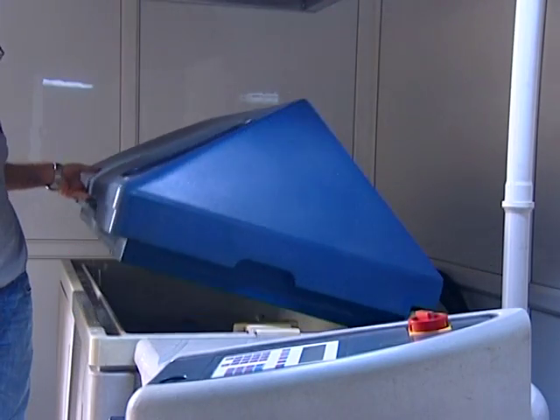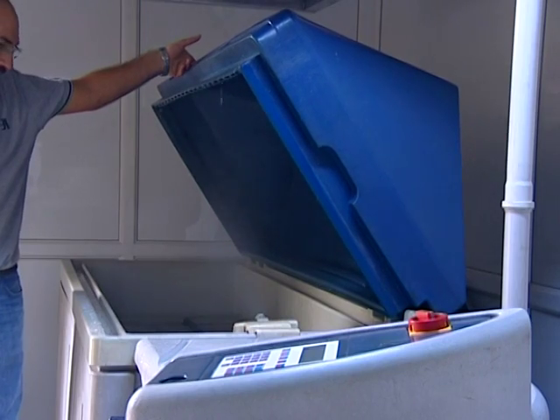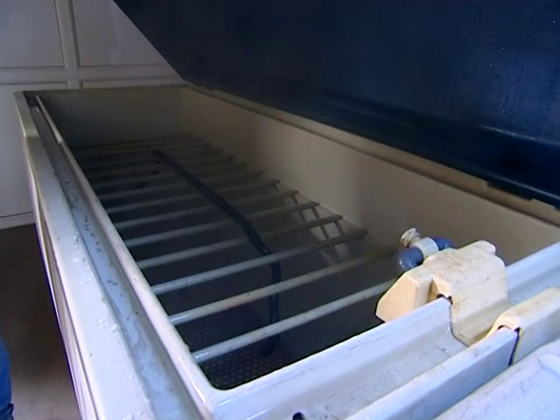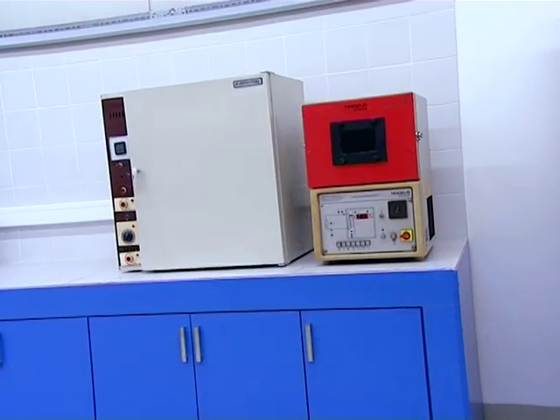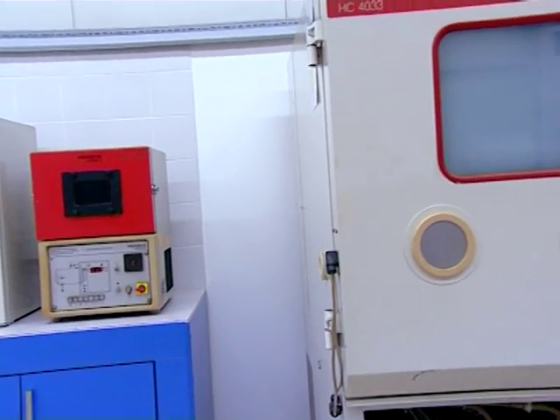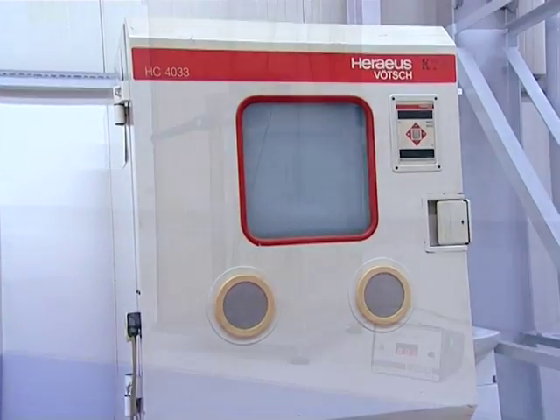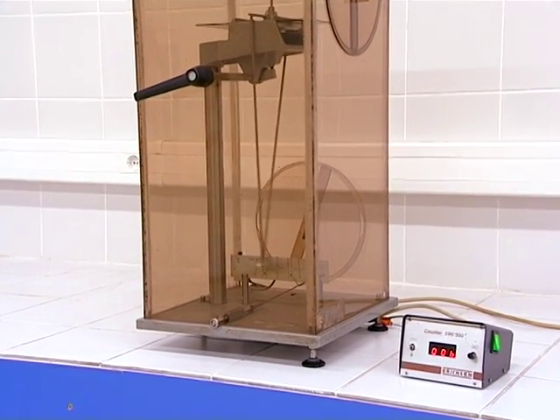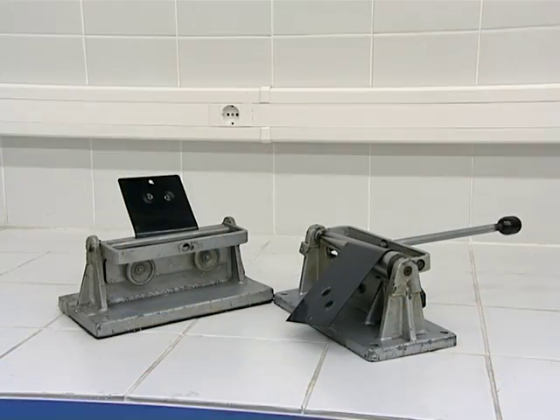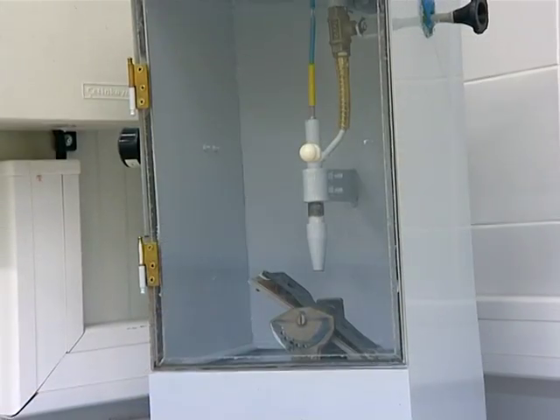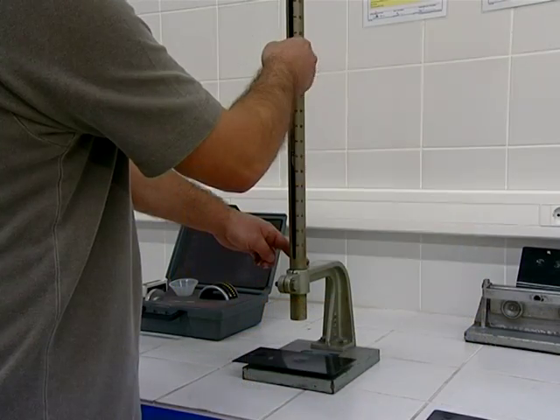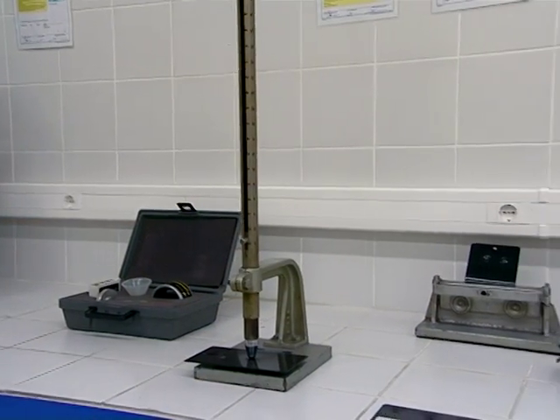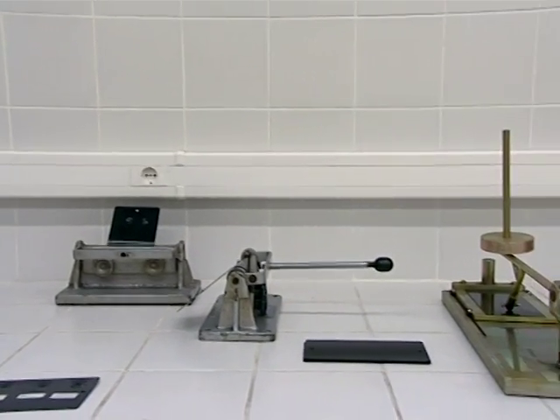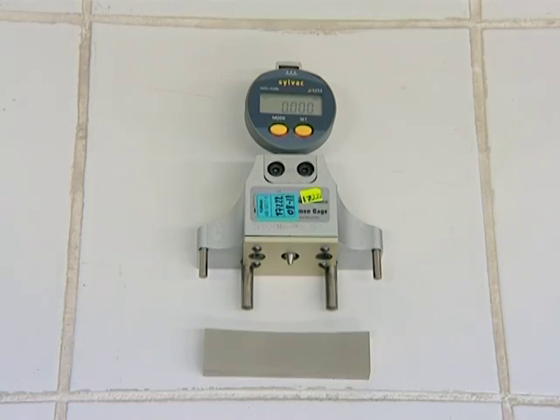For the control of the paint process, a Votsch VSC KWT 1000 salt spray test machine is used for corrosion resistance. A Votsch HC4033 climatic test chamber is used for temperature and humidity resistance. The Erichsen pendulum test device is used for paint hardness determinations. Conical and cylindrical mandrel bend test, paint abrasion, crosscut, stone chipping, paint thickness, and paint impact test equipment is also present. For the evaluation of the effectiveness of shot peening, Almen intensity measurements, surface coverage evaluations, and shot size screen analyses are carried out.